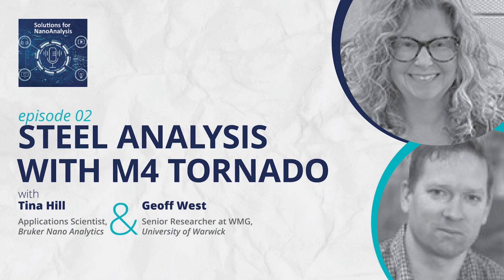One of the selling points of XRF is that sample preparation doesn't need to be great. Okay, and obviously I think people often take that too literally. Because for steel, we always see that the interaction volume is something between 5 and 10 microns, something like that. So if you want nice Bragg diffraction, if your sample has got a pile of cold work in the surface, loads of deformation, I can't see how you're going to get good Bragg diffraction, because you're not going to have a clear grain structure there.